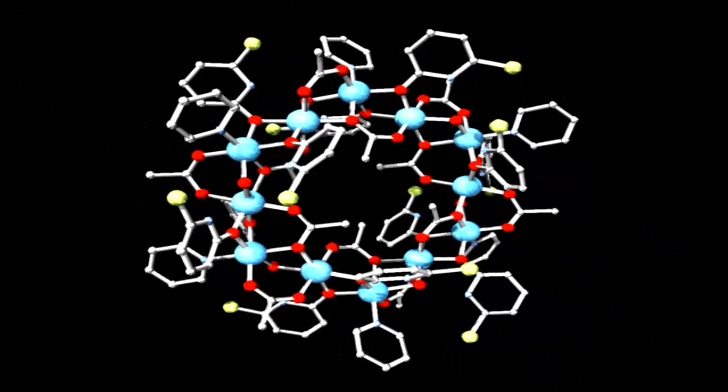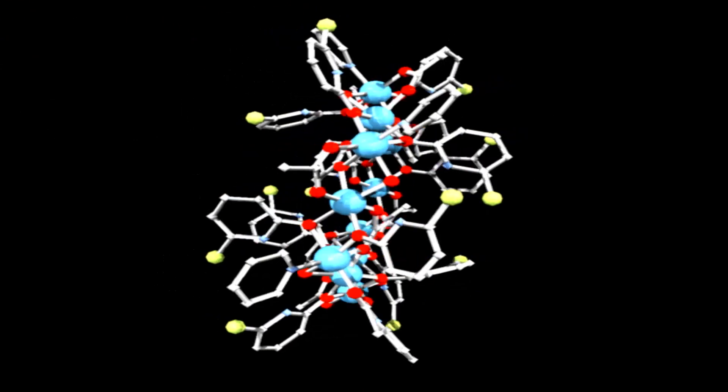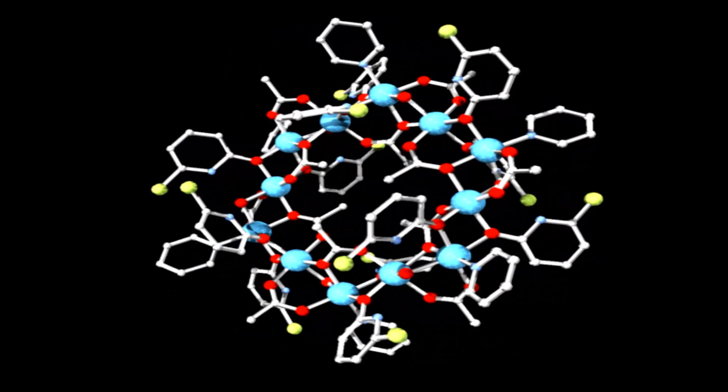We've used these metal molecules and we are able to arrange these in a ring-like structure. Because there's a large hole, what happens is the density goes down, so that means there's less to scatter on and you'll have a smaller feature size.